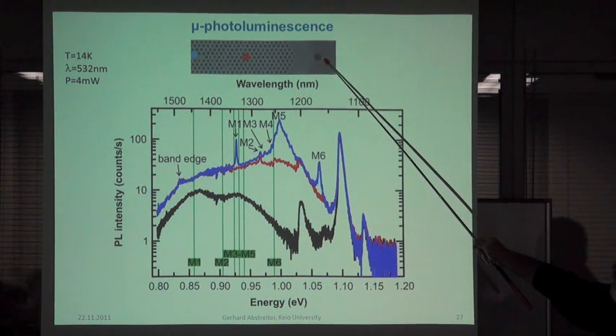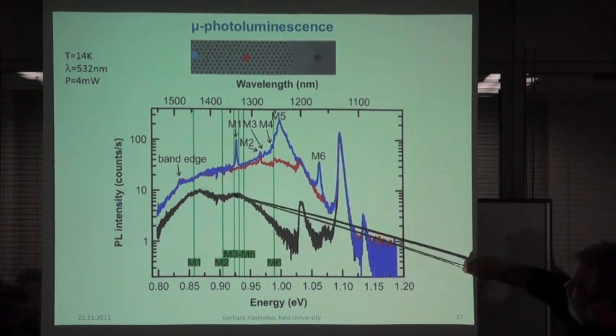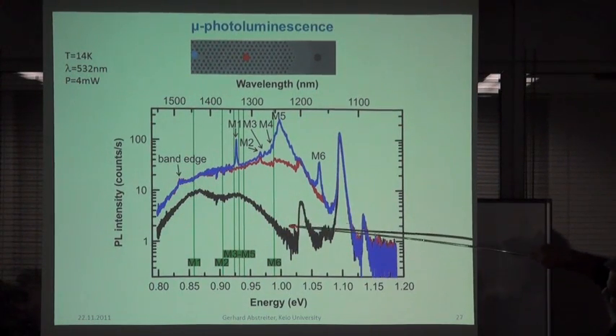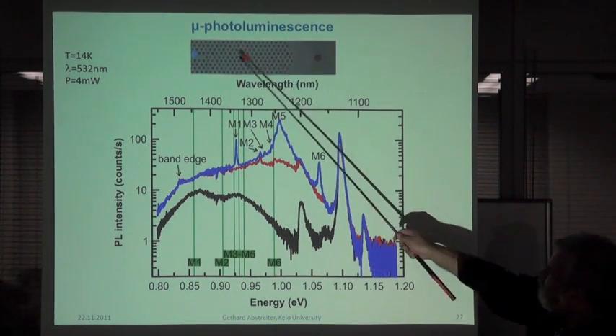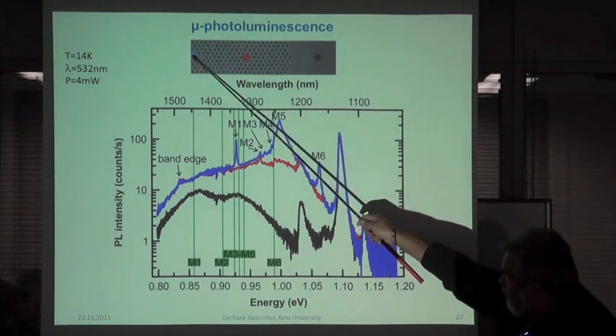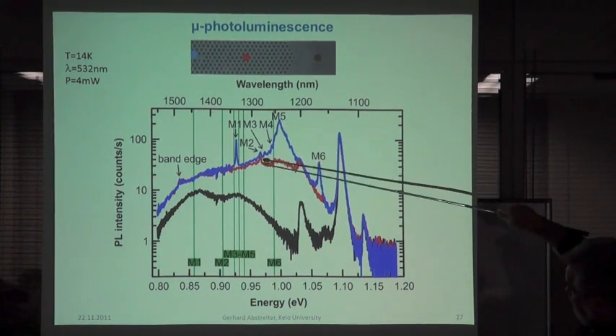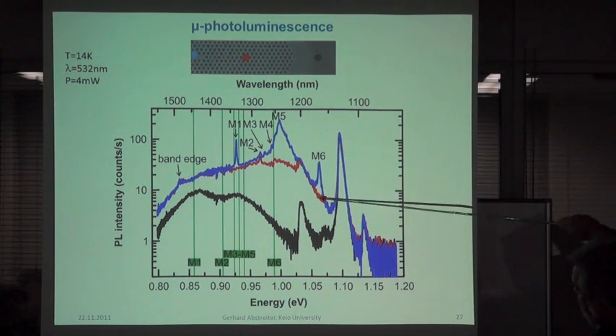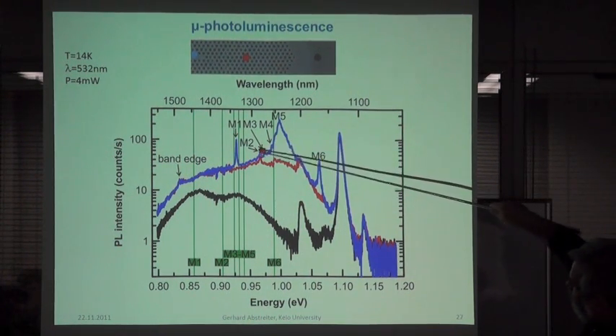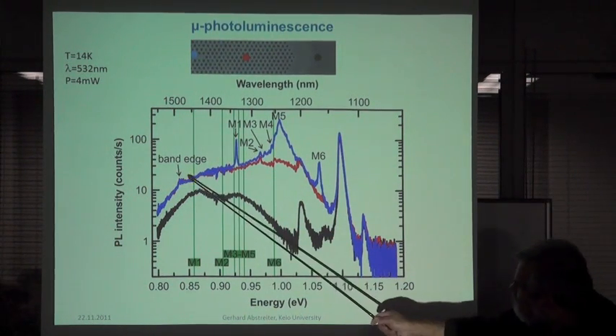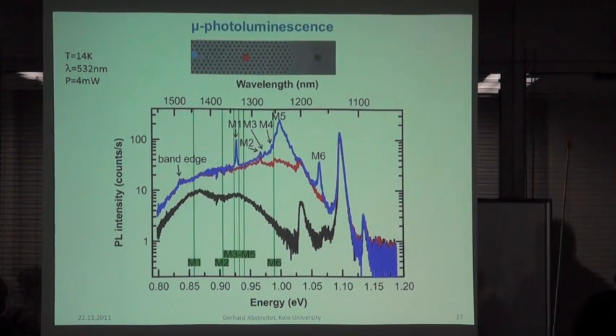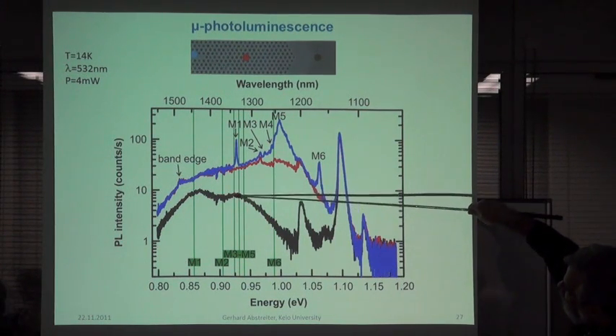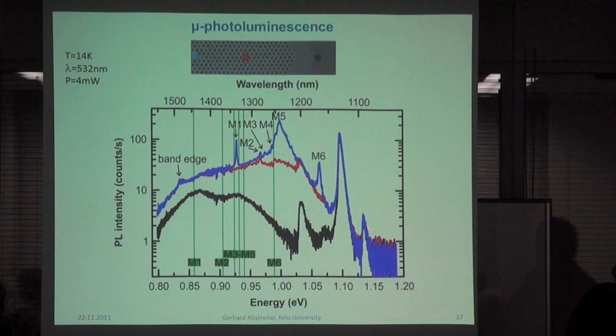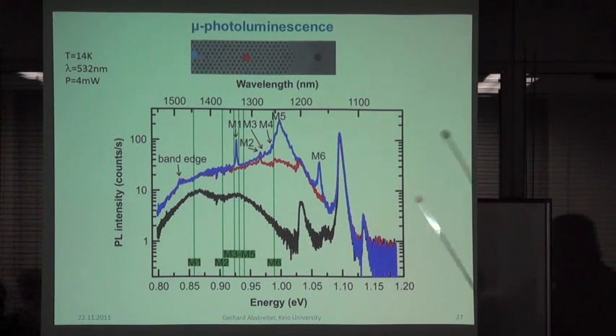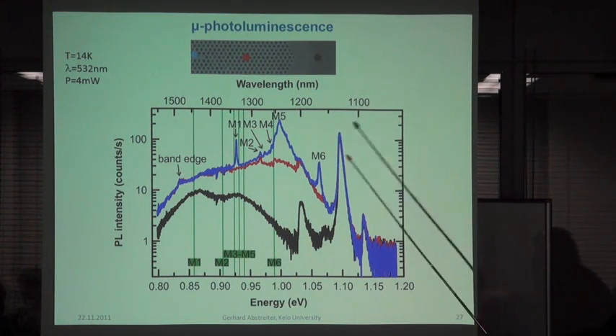This is measured outside. Now, when I just go onto the photonic crystal, I see already an enhancement of the emission by maybe a factor of 10. And then when I go into this cavity, into this defect here, I see these cavity modes which have different widths. This may be overlapping several ones, and this is one of these modes, and this is the end of the photonic band gap. And you see, in these modes, we get an enhancement of the luminescence maybe by a factor of 100, depending where you are. And this is mainly redistribution of the light, outcoupling, but it's also Purcell effect if the cavity is good enough here.